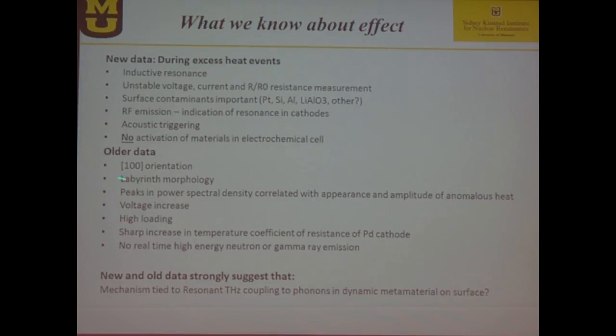Now we also know that it's important to have orientation of 100 on the cathode, because that helps to get high loading. Labyrinth morphology, peaks in power spectral density correlating with the appearance of excess heat, as I showed, voltage increase, high loading, sharp increase in temperature coefficient of resistance of palladium cathodes, and again, no neutrons, no gamma